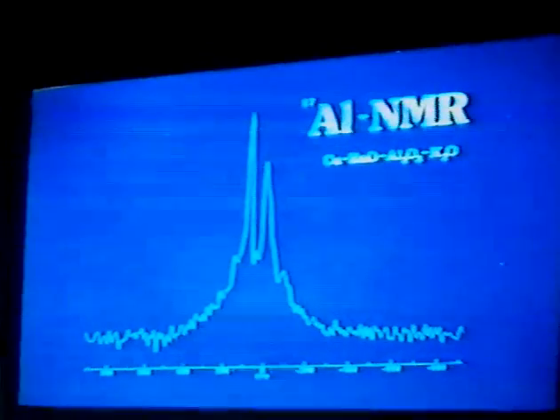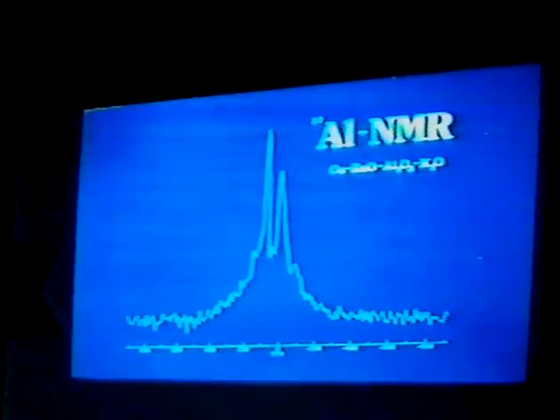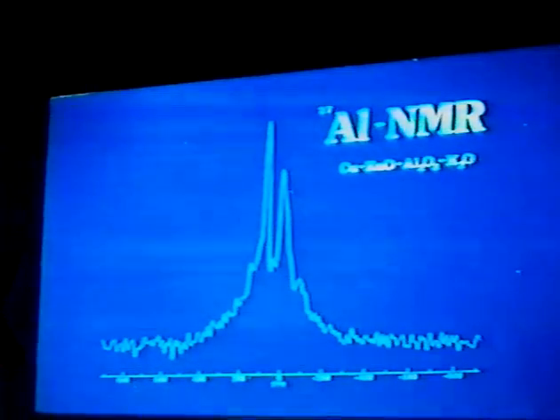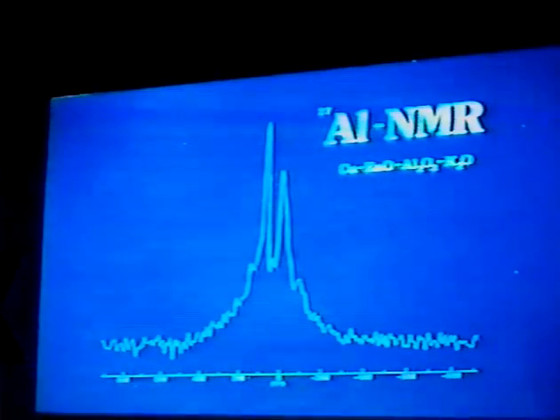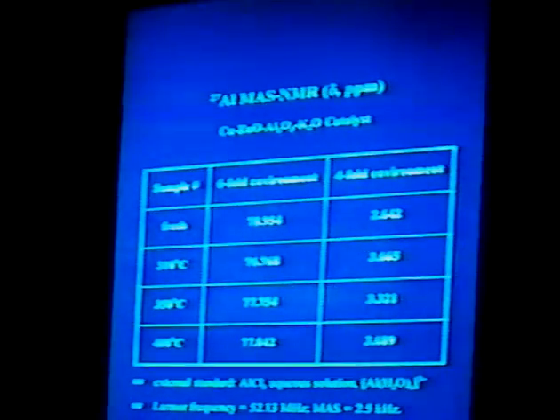But what about other elements here? Doing the magic angle spinning NMR for the aluminum, you can see mainly two resonance signals. Since we use aqueous aluminum trichloride as the standard, this one probably is the 6-coordinated aluminum, and this one is the 4-fold environment. All of the experiments show similar signals, only the chemical shift changes a little.